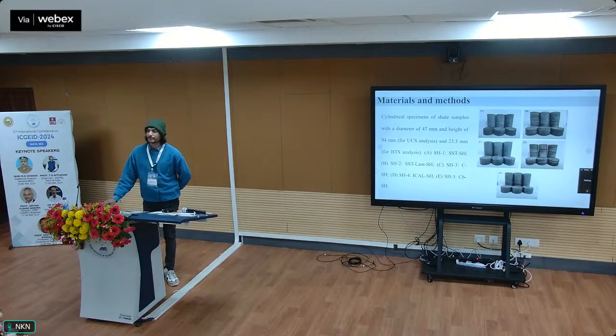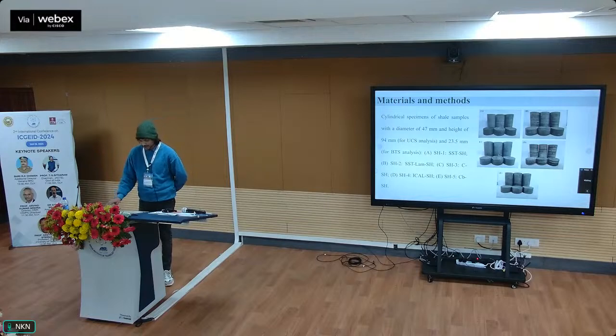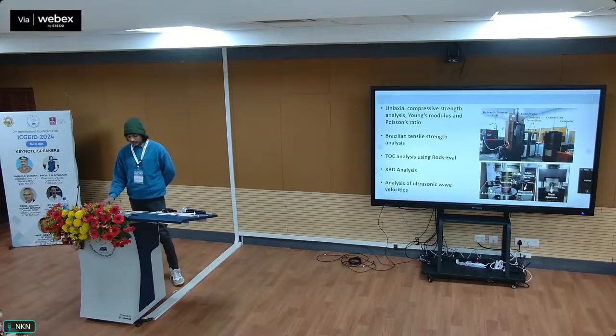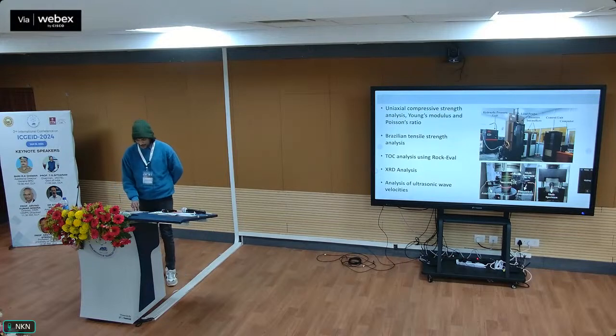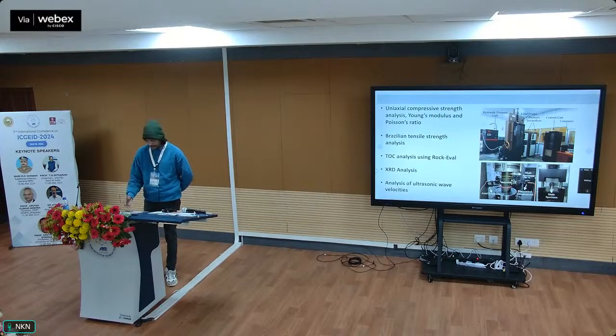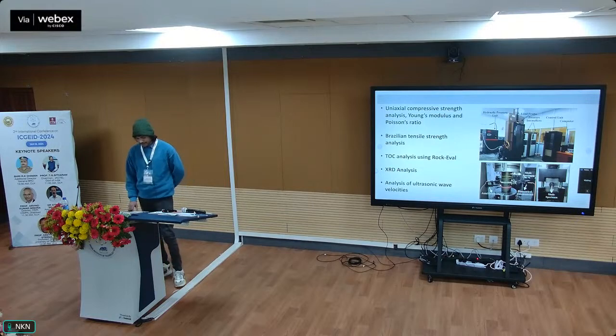The samples were first prepared for mechanical properties analysis. These are prepared as cylindrical specimens in both sizes. One is length to diameter ratio of 2 and another is length to diameter ratio of 0.25. The standard followed was ASTM. The diameter of the samples was 47 mm. The UCS, Young's modulus and Poisson's ratio, the mechanical properties of these shale samples, were obtained from the MTS system, a rock mechanics test system at CSIR SIMFA. The TOC, total organic carbon, was calculated using Rock-Eval. We also calculated the mineralogical composition of the samples using XRD, and also the physical properties to evaluate whether microcracks are there or not. We calculated it using ultrasonic wave velocities, P and S wave.